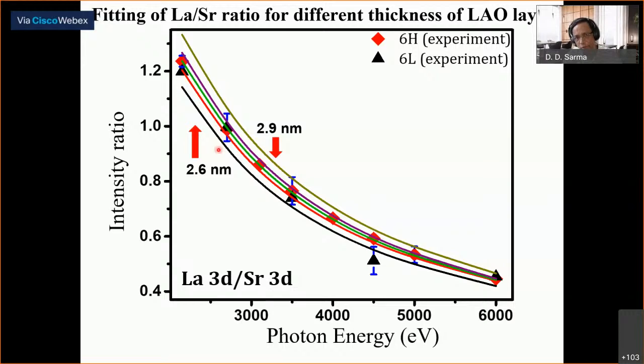And you can see this top brown line is for a 2.9 nanometer thick lanthanum aluminate, and this dark line at the bottom is 2.6 nanometer, and that covers all the experimental data points, saying that this technique can pin down the thickness of the LAO layer on top between 2.6 and 2.9 nanometer, which is 0.3 nanometer, so plus minus 0.15 nanometer. 1.5 angstrom thickness uncertainty at the most. But of course, we being the practitioners believe that the actual error is even smaller.